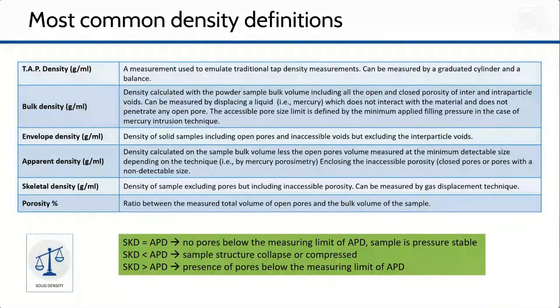The bulk volume is comprehensive of all open plus closed pores and voids between the particles. It can be measured by mercury porosimetry when the sample is under vacuum. The apparent volume excludes open pores, and it is comprehensive of closed pores and pores that cannot be measured with the applied technique. For instance, mercury porosimetry has a lower limit of 3.6 nanometer size. Finally, the skeletal volume measured by gas pycnometry is the material volume comprehensive of only closed pores, if present.